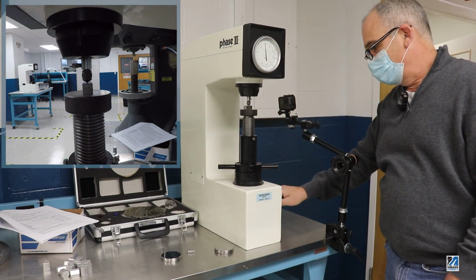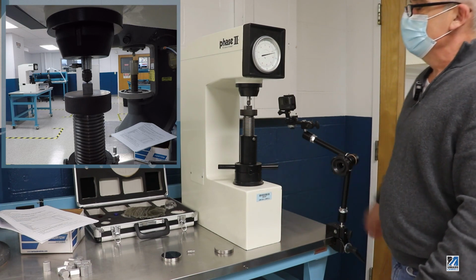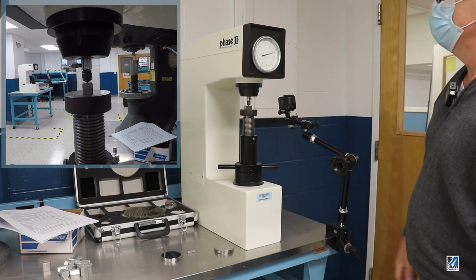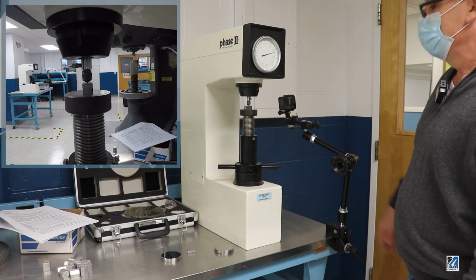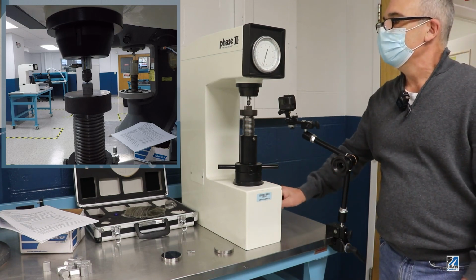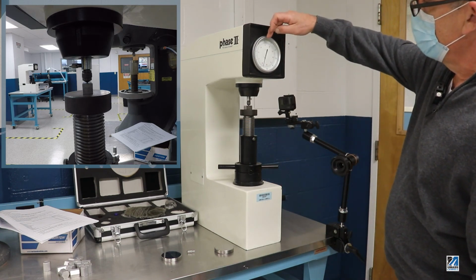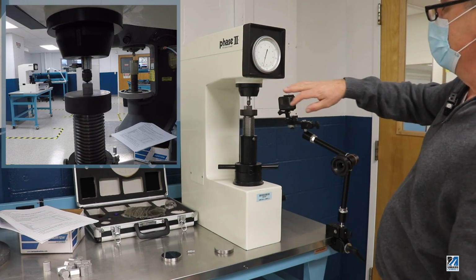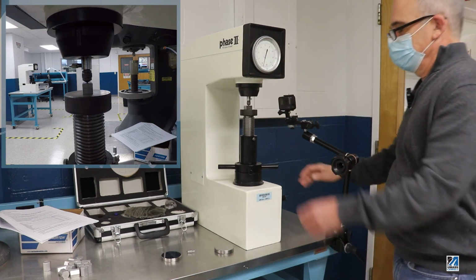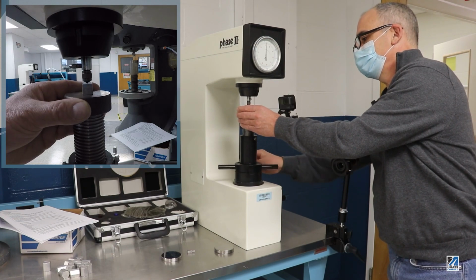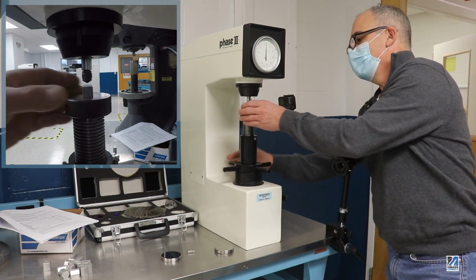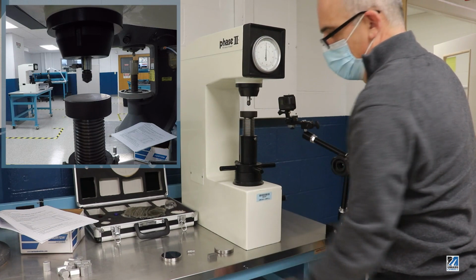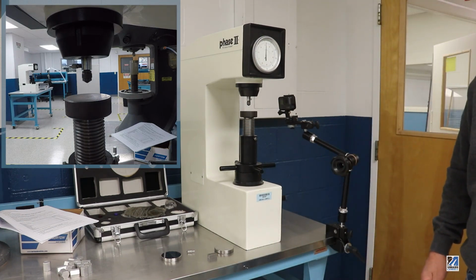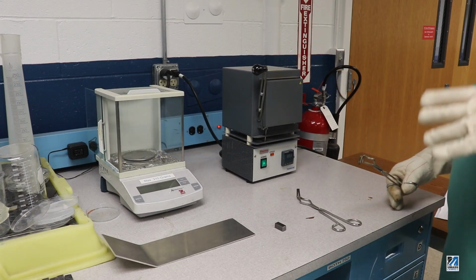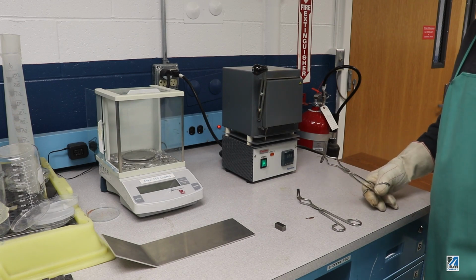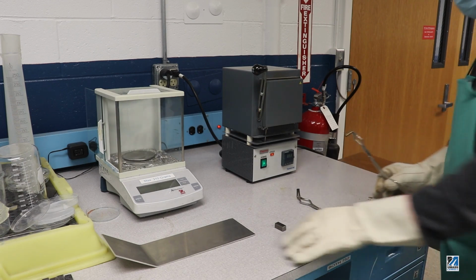Again, apply my major load. Wait for the needle to stabilize. Remove the major load. And now I can record my Rockwell B of approximately 87. I'll remove the sample, and that takes care of that portion. Okay, so now we've done the preliminary hardness test with the Rockwell B on the 1018 sample.